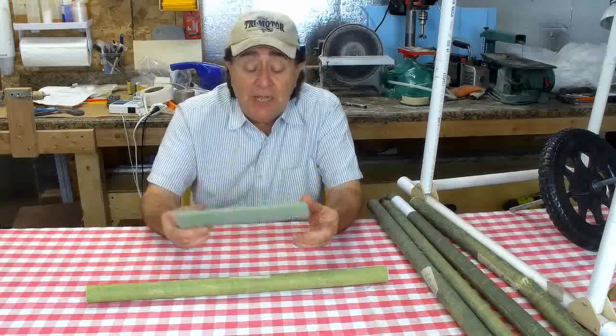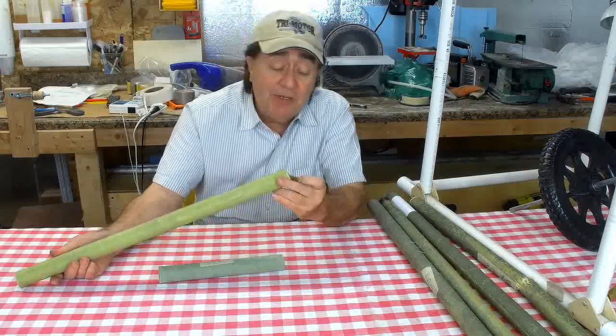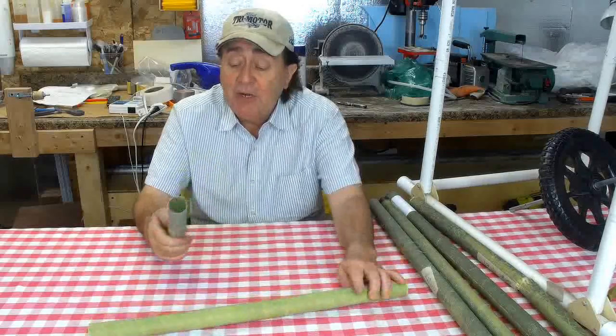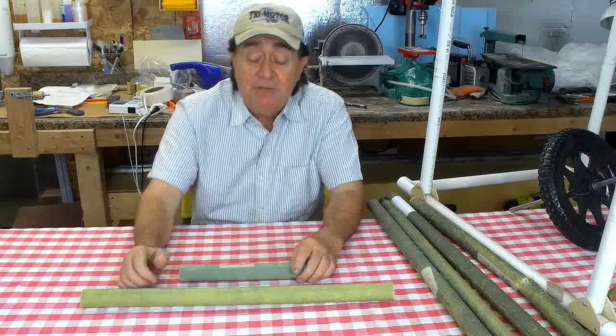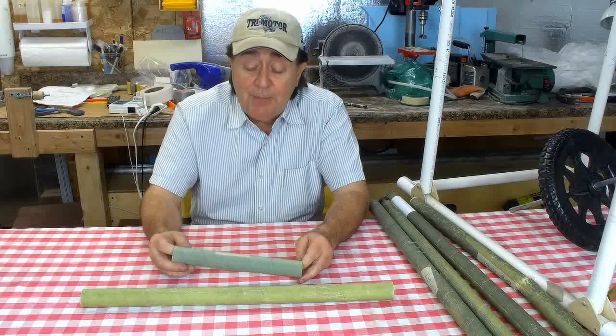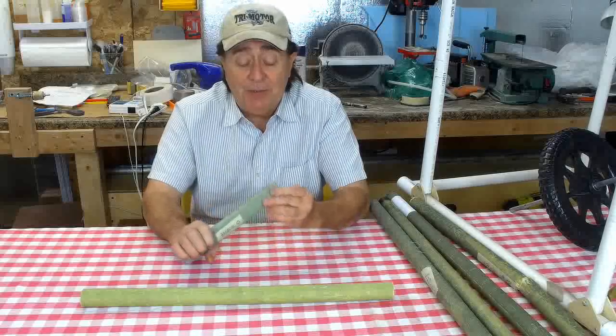This one is fiberglass. I thought, you know, with a sandwich panel method, maybe you really don't need the carbon fiber for all that strength and stiffness. And I made one out of fiberglass. It'd be a lot cheaper: $17 to $20 a yard for the carbon fiber, $8 a yard for the fiberglass. So there's cost savings there. This one came in at 0.76 ounces per foot, even lighter. Feels like you're picking up paper with this thing.